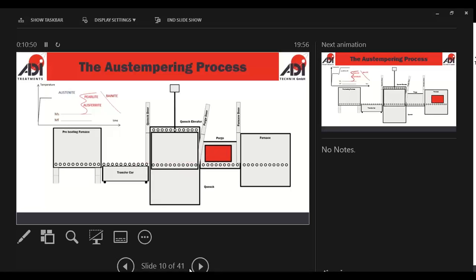So this part of the furnace is called the purge. All of the heat treatment is done under a protective atmosphere, but this protective atmosphere reacts with oxygen in the air and can cause a bit of a bang if you mix them together. So what we have to do is remove all the air before we put the parts into the back of the furnace. Once we're in the back of the furnace, obviously we heat the parts up to that 850, 900 degrees centigrade.